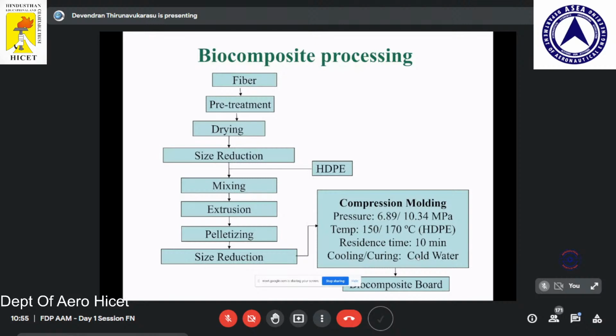Fiber pretreatment uses alkaline treatment or acid hydrolysis. We dry it, and then size reduction. Then we mix it with high density polyethylene, then the extrusion process, pelleting and sizing. Finally, in the compression molding process, with the parameters I explained in the previous slide, we get biocomposite boards for various applications.